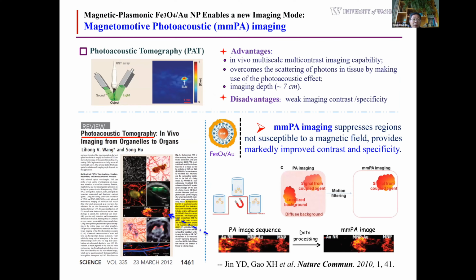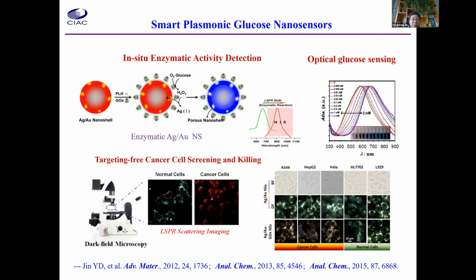More importantly, based on magnetic plasmonic iron oxide gold core nanoparticles, we developed a new biological imaging modality called magnetomotive photoacoustic imaging. Since it suppresses regions not susceptible to a magnetic field, it profits from markedly improved contrast and specificity. So it is envisioned as very promising for potential clinical use for early detection of cancer.